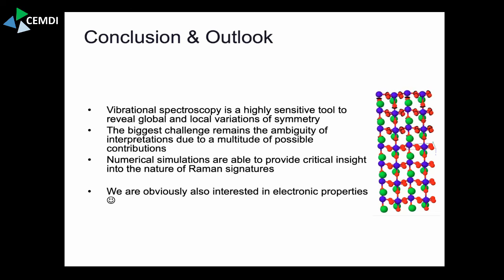In barium titanate, I think Ifani Chukwu did this in his PhD thesis, we would see the Raman signature of barium carbonate. And the peak of barium carbonate would become ever so bigger as you increase the surface to volume ratio. It just becomes more significant if you make smaller particles because you have more surface. So the chemisorbed species have a pretty clear signature. What is way more demanding, and a scientific discipline which is really in its infancy, is surface reconstruction.